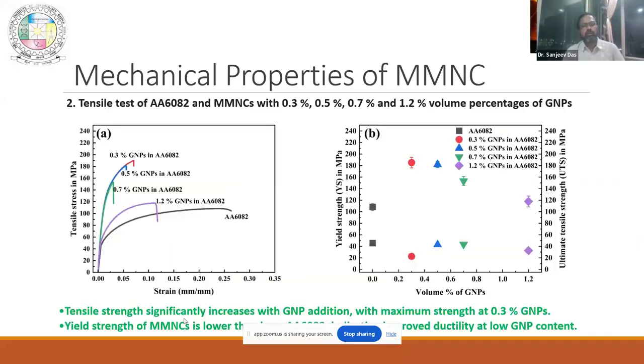Some of the mechanical properties you can see. Now this is the beauty. You have the tensile graph of the alloy, and you see all the composites have higher strength. If you do it with macro particles, the strength is never going to go high. It will have premature failure. Here there is premature failure. You can see in the graph the elongation is not high. It is failing while rising for all the composites. But the strength is definitely increasing. That means it is contributing, it is resisting the motion of your deformation.